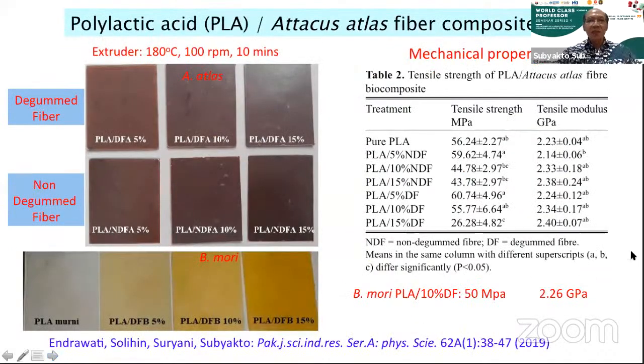This is the composite that we make from the PLA and the Attacus atlas fiber. And we use the degummed fiber and non-degummed fiber. And this is the processing. And we use 5, 10, and 15% weight. And compare with Bombyx mori. And we can see here that Bombyx mori, the color is lighter compared to the Attacus atlas.